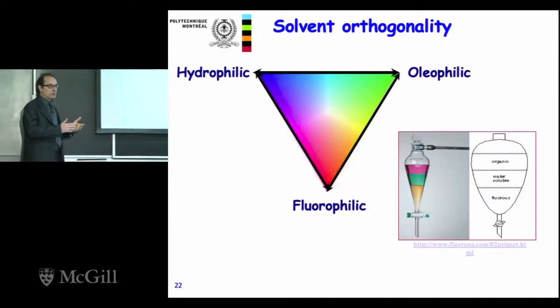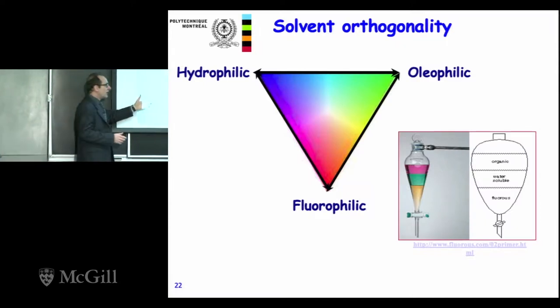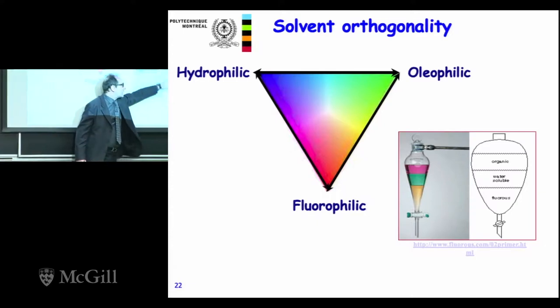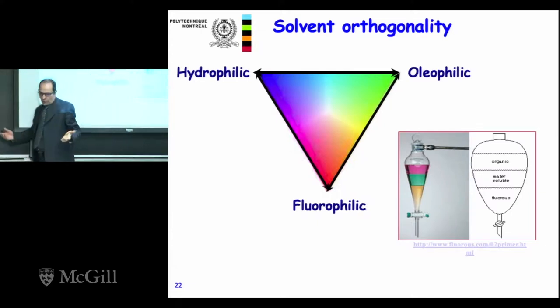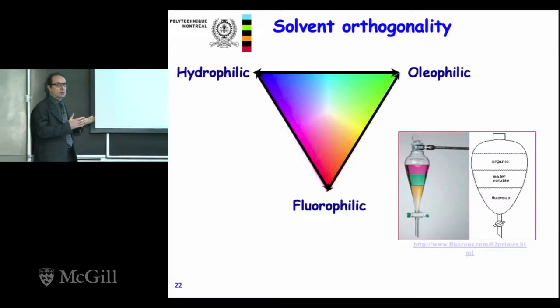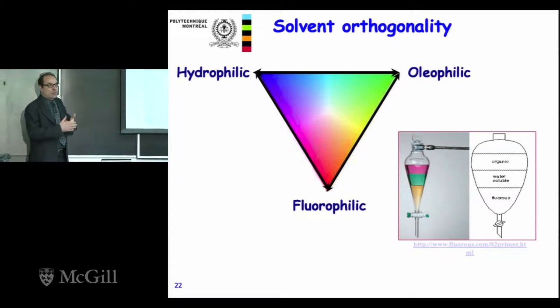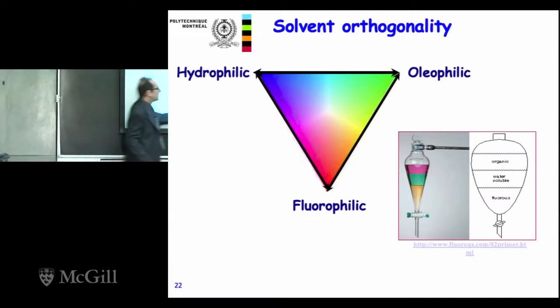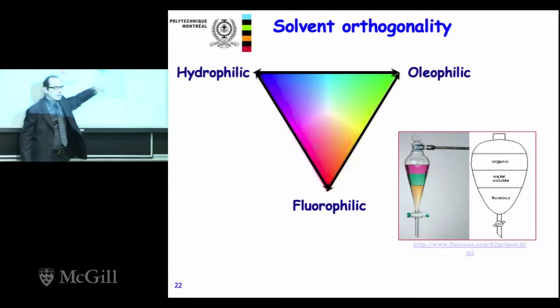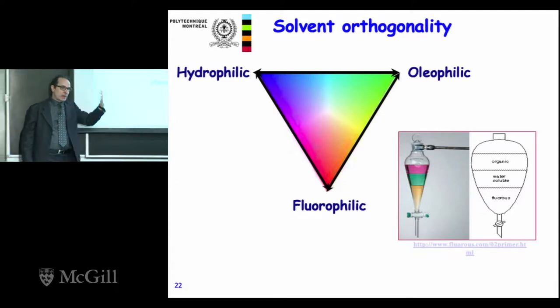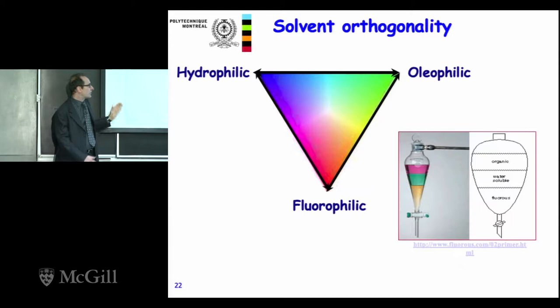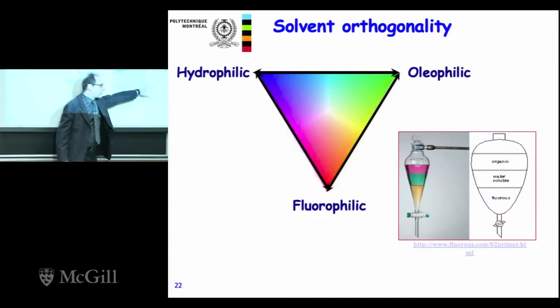So if you base all the lithography on fluorinated material, you're not going to destroy your conducting polymer, which is an organic material. Actually, all the photoresins that are now used for silicon photolithography, they are organic, so they would destroy this material by decreasing the conductivity and sometimes even by just dissolving the film. So if we use these materials, we are completely safe.